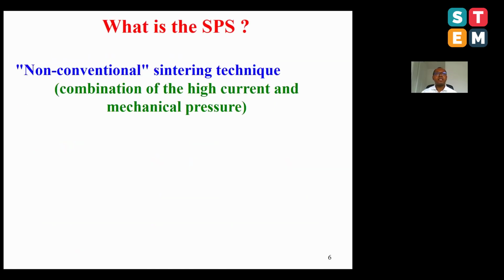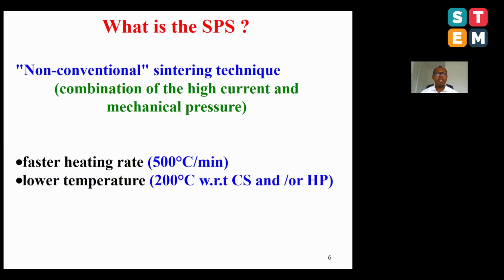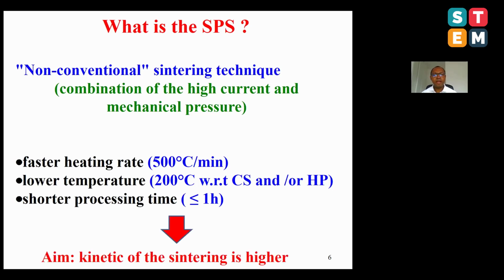What is spark plasma sintering? This is a non-conventional sintering technique where we combine very high current and high mechanical pressure to prepare the materials. It gives a faster heating rate, up to 500 and sometimes 1000 degrees C per minute. With lower temperature, you can sinter 200 degrees C below the temperature used in conventional sintering or hot pressing. It also gives a shorter processing time, less than an hour. Basically, the main aim of this technique is that the kinetics of the sintering is quite higher.